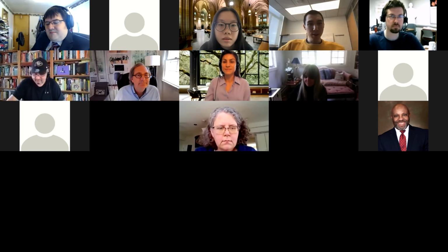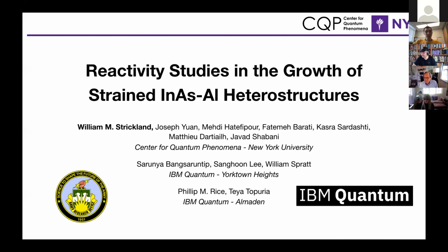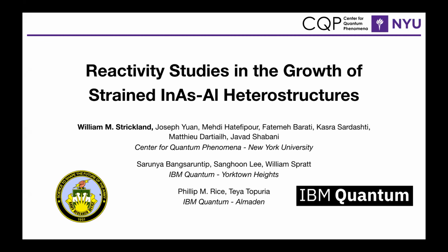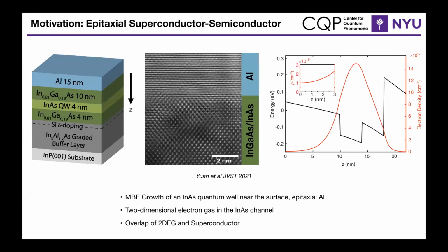Cool. Thank you, Chris. Yeah, thanks for the introduction. Today I'm going to be talking about reactivity studies and the growth of strained indium arsenide aluminum heterostructures. This work was funded by the Army Research Office, and done in collaboration with researchers at IBM Quantum. In our group, we focus mainly on near-surface indium arsenide quantum wells, and we grow these by molecular beam epitaxy, and we're able to contact these with a thin aluminum layer for a superconductor. Doing this in situ, in the growth chamber, we're able to get a nice interface between the aluminum and InGaAs and indium arsenide layers. This is seen in the TEM image here by an atomically flat interface. What's more, what's seen here is a simulation of the electron density, and it is very well confined in the indium arsenide 2D channel.